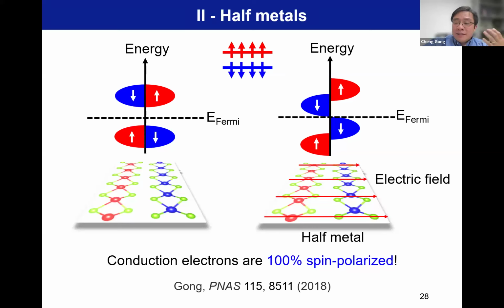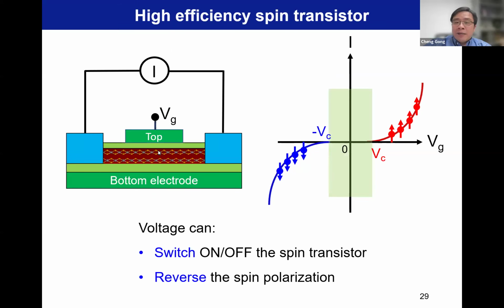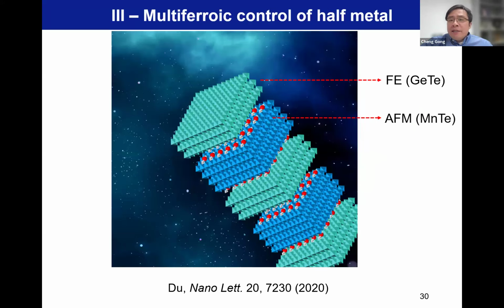And then this 100% spin polarization is great for spin FET. So you can build such a device, A-type anti-ferromagnet, use a voltage to create half metallicity, turn on and turn off the half metallicity. Or you use a positive or negative voltage to push spin up or spin down electron to the Fermi level. So like a transistor, you can switch, you can reverse the polarization. Transistor is reversal between electron and hole, but here is a reversal between spin up and spin down electron. So the third part, I will go very quickly because this is a combination of the first two ideas.